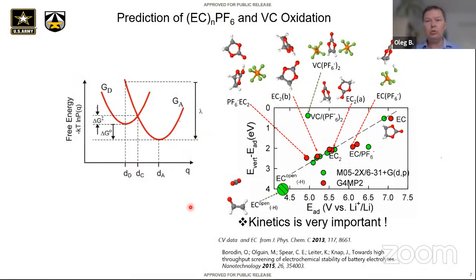So now let's go to what the relevant components are. When I started working in this area quite a while ago, I saw that the majority of groups were just taking a solvent like EC or PC and calculating its oxidation potential, often looking at trends. Even if you include the polarizable continuum model, do geometry optimization, and ensure by comparison with the NIST database that your ionization potential is quite accurate, you are still getting about 7 volts. Of course, if the electrolyte were stable at 7 volts, we would be done. So clearly there is a disconnect, and EC is not getting oxidized by itself.